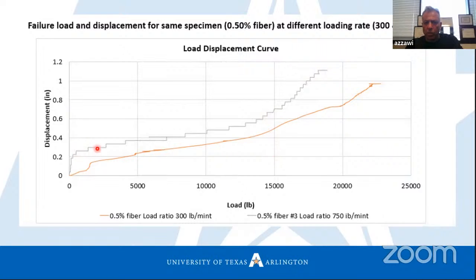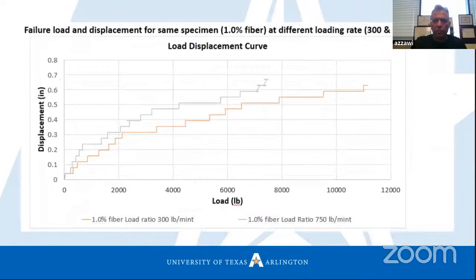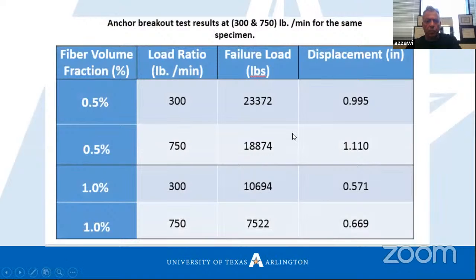And as we see, increasing the loading rate will decrease the strength. That's expected. The high loading rate will not give us that much strength, and also will increase the displacement, as we see. A low loading rate improves the strength and also reduces the displacement at the anchor bolts. We did this also for the other specimens, which is 1% fiber for both loading rates. So a high loading rate reduces the strength, and a slow loading rate increases the strength and reduces the displacement. These are the results we obtained from the experiment.